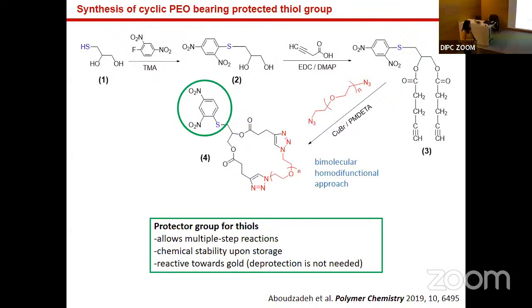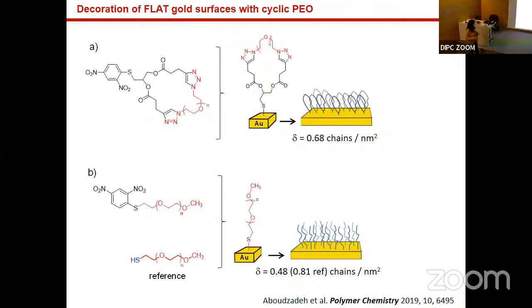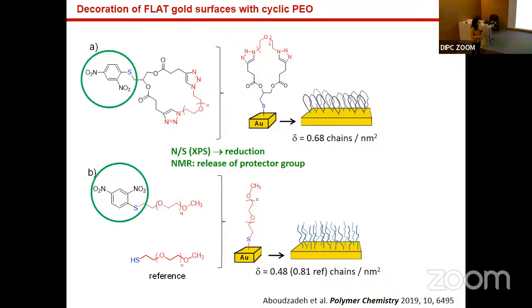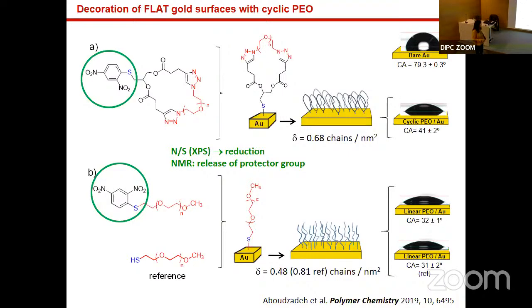In this case, we have to protect the thiol group, and we observed that the protecting group for thiol was very convenient because we can leave it in the polymer, and it's good for storage and so on. Then we modified flat surfaces because we wanted to demonstrate whether this reaction was possible. We demonstrated by XPS and NMR that this group is released, that the polymer is attached by a thiol group, and that the surfaces are modified with the cyclic polymer, and we did the same with a linear equivalent.